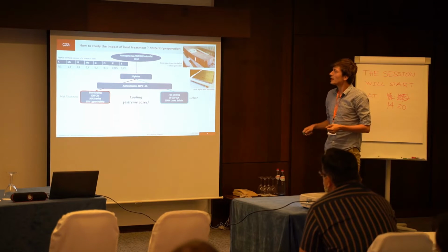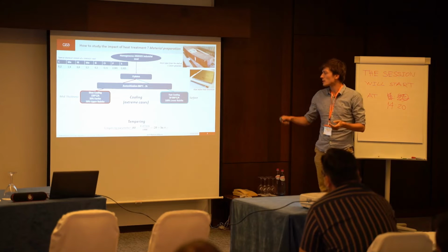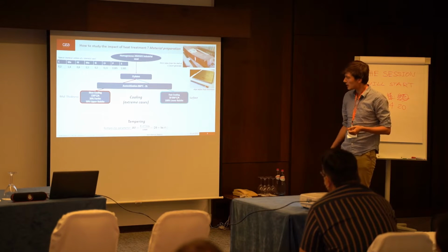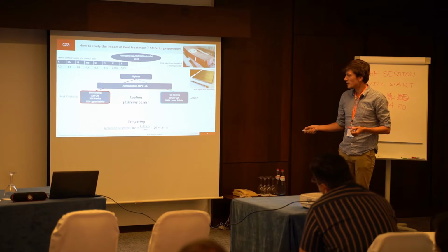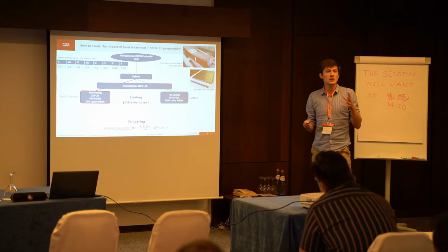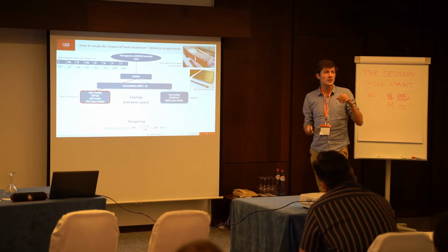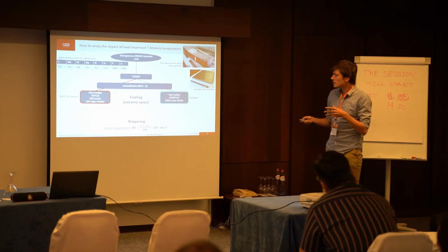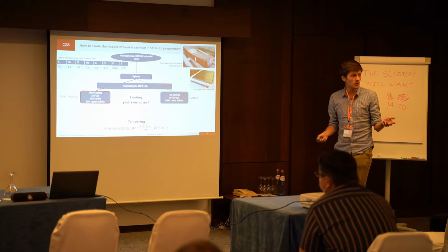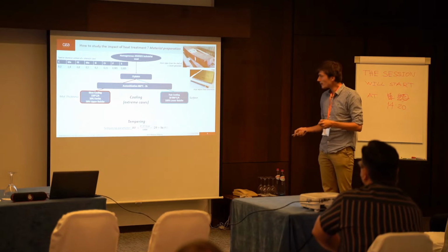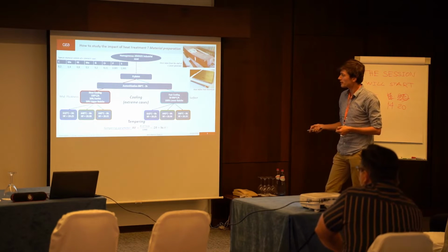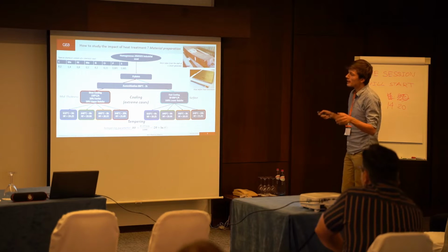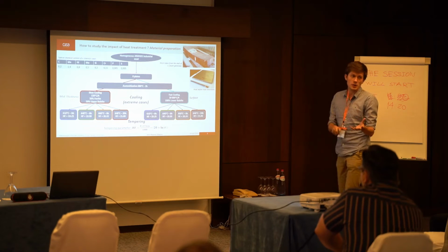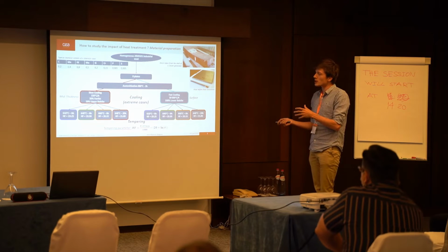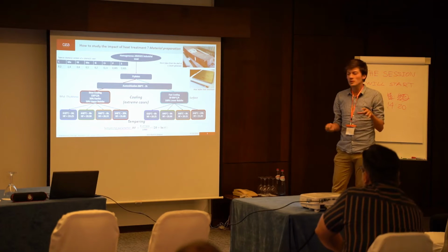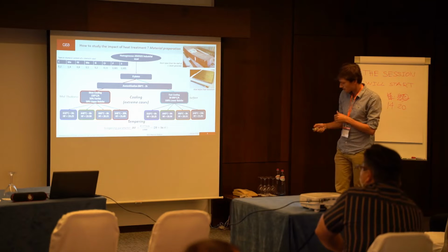And since we are studying the impact of heat treatment conditions, we are also going to study the effect of tempering. Here we introduce the tempering parameter. It's a quantity that is used to estimate the intensity of tempering by using both the tempering temperature and the tempering duration. And we are going to consider 4 different tempering conditions, and we explore both the effect of temperature and tempering duration. Here for this study we will just use the tempering parameter.